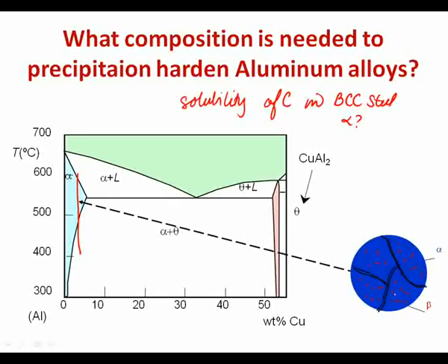Yeah. They'd be larger, right? Now, nucleation is harder, growth is easier, so we have bigger precipitates. Also, because growth along the grain boundaries is much easier, we might get them growing along the grain boundaries. And that's something we don't want. We don't really want a very thick, hard layer of precipitates at the grain boundaries, usually.